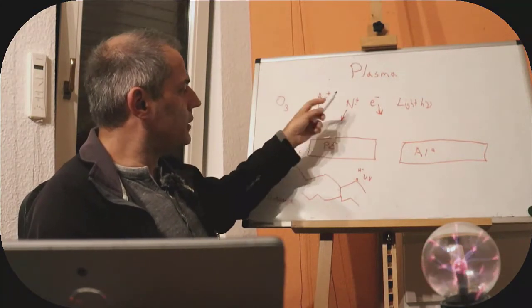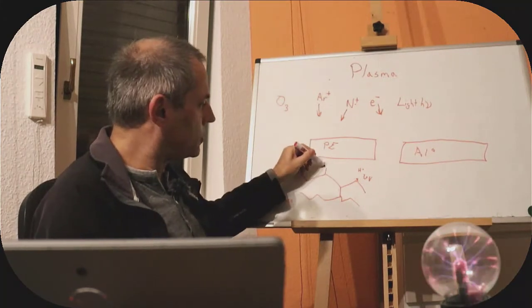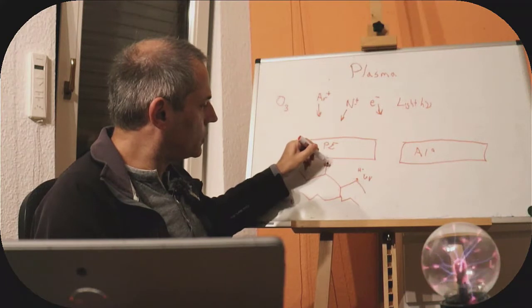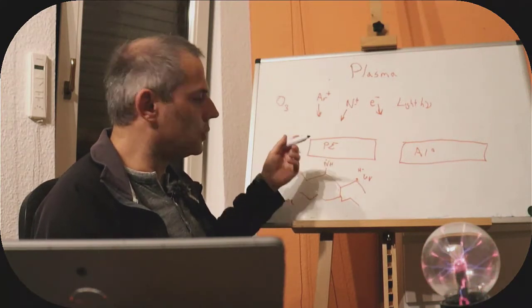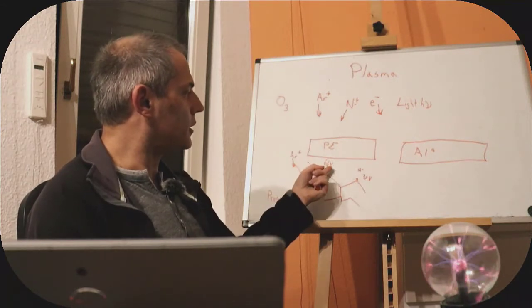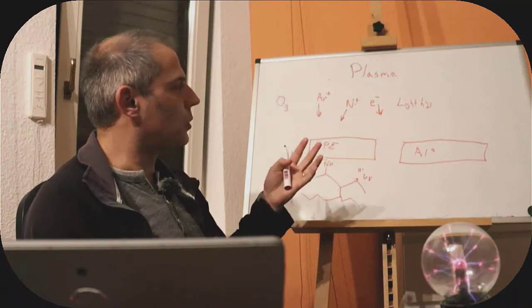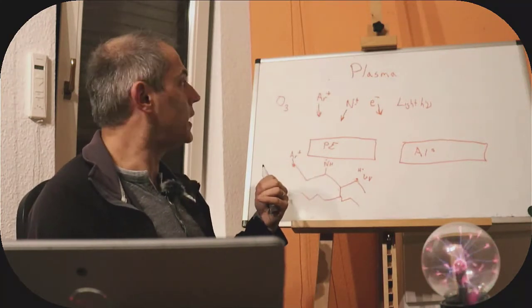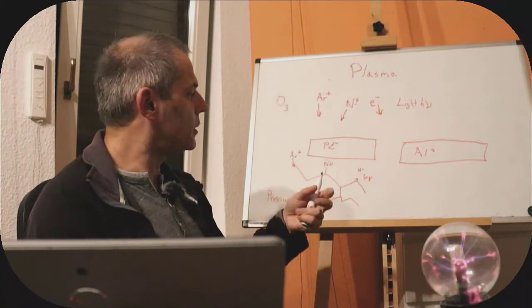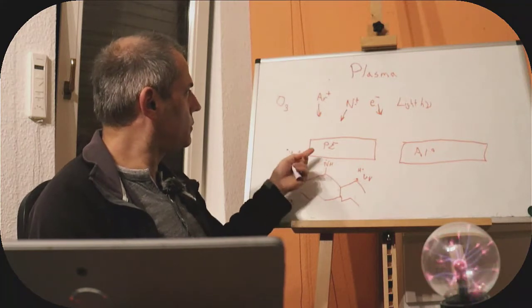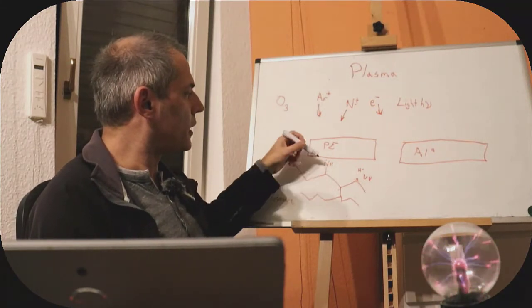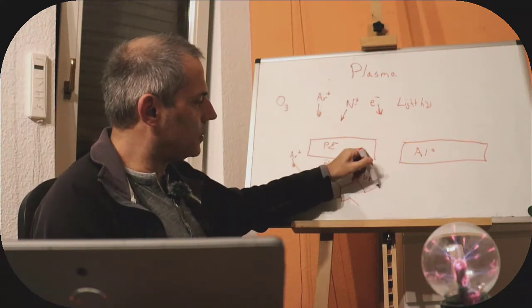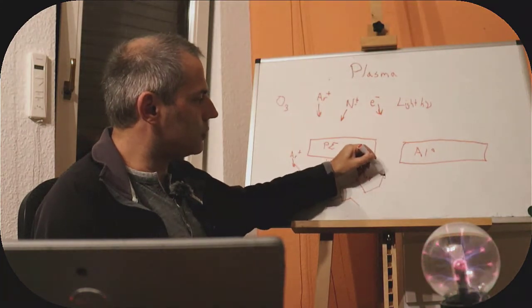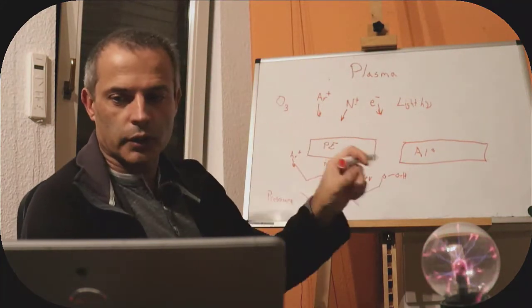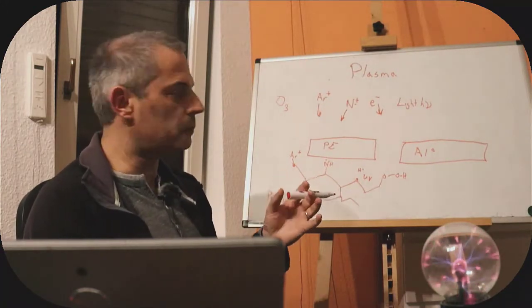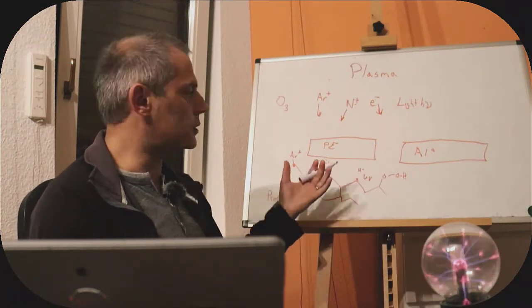And then the reactive gases can actually react with the surface to add new chemical groups to it. So we would form maybe NH dot, because we've added a nitrogen species and the hydrogen that was on there, so it's squeezed in the bond, but obviously that's going to react further when we get into the air. Ozone likely can do the same, so it can interact with these surfaces, causing them to react, and it can graft an oxygen into a bond, so it can graft an OOH on there, putting the O2 in the middle of a CH bond. That is a peroxide group, and it is now quite reactive.